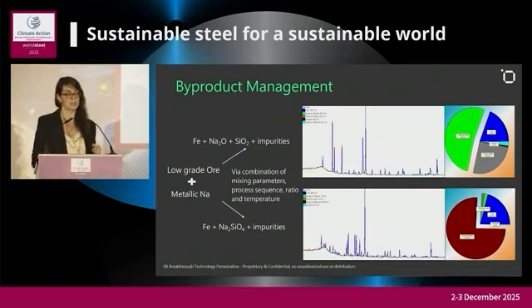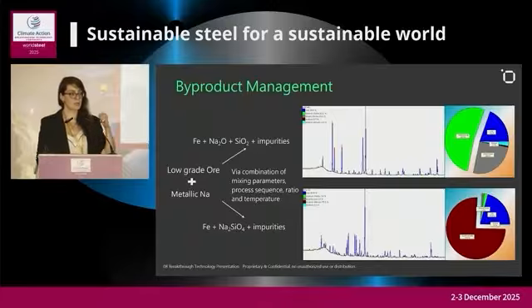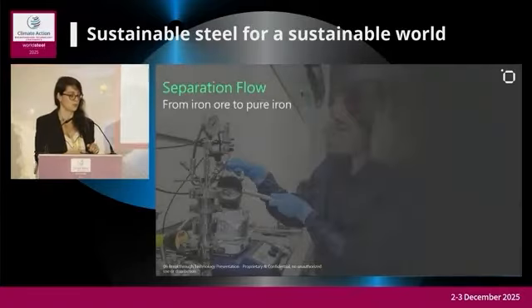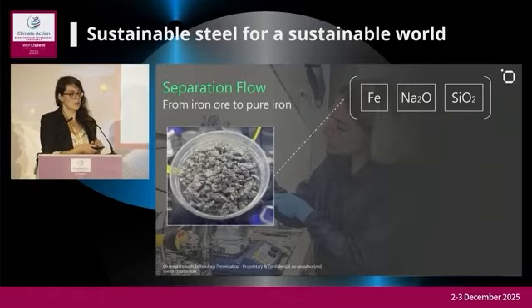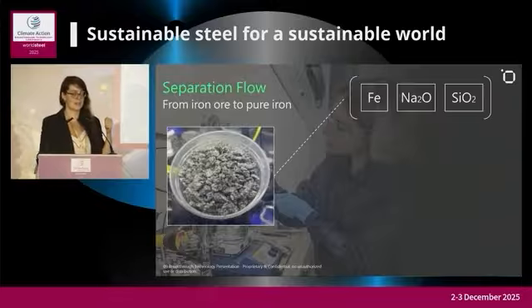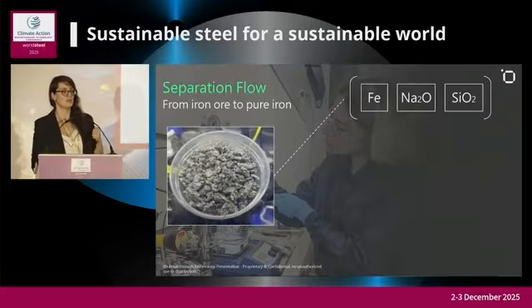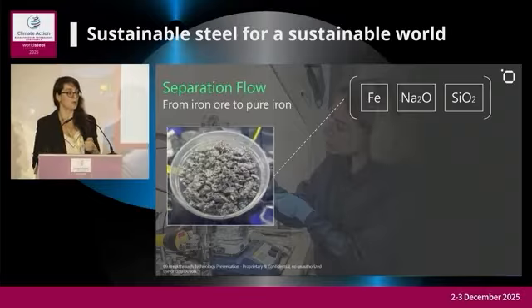And why is it important? It is important because by controlling this outcome, we can control the separation methodologies that we want to use. So the separation flow is, again, we are starting with the reduction results. For example, here the Fe metal, sodium oxide after the reduction, and the silica as the gangue. The other impurities, in most cases, we found out have an affinity bond to the sodium metal. And therefore, in most cases, these are the outcomes after the reduction: Fe metal, sodium oxide, and silica.